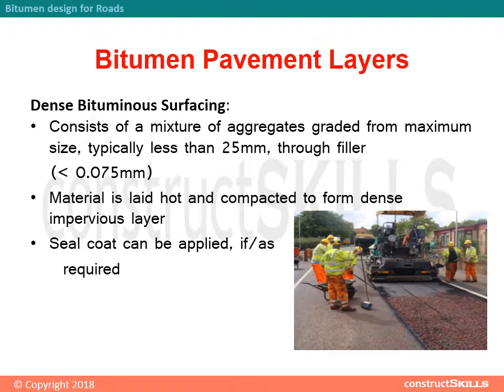Dense bituminous surfacing consists of a mixture of aggregates graded from a maximum size typically less than 25 mm down through filler less than 0.075 mm. The material is laid hot and compacted to form a dense, impervious layer. A seal coat can be applied if or as required.